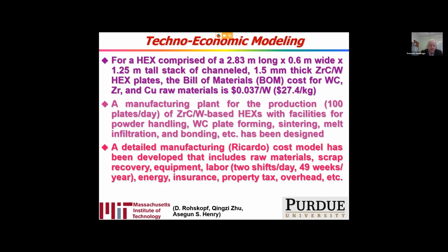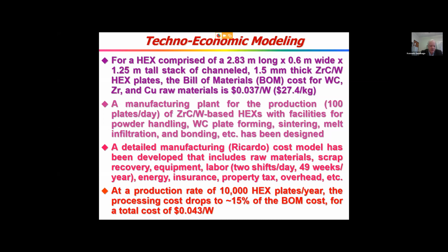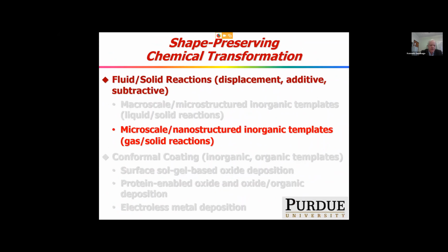Professor Henry then used a Ricardo model, which is an Excel spreadsheet model inherited from the automotive industry, with incredible detail on costs, raw material scrap, equipment, labor, energy, insurance, property overhead, property tax overhead, and much more than I'm saying here to cover the processing cost. And what they discovered was that at a production rate of 10,000 plates per year, which for this heat exchanger corresponds to about 13 heat exchangers per year, the processing cost drops to about 15% of the raw material cost for an overall cost of about 4.3 cents per watt, which compares very favorably to nickel-based superalloys, which don't have the properties that these materials have, made by the conventional etching process, and we think even favorably to stainless steel etched heat exchanger plates. Again, they don't have the properties that our material has. So that's a quick example with that process.